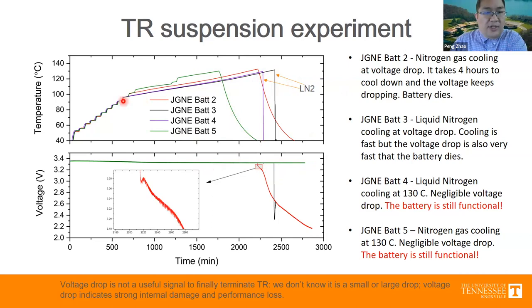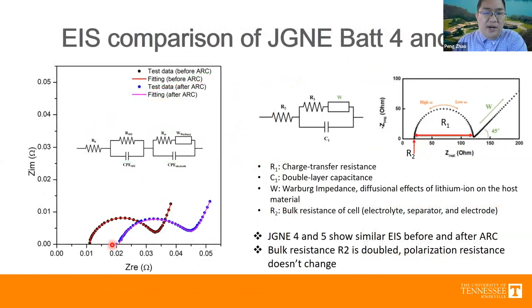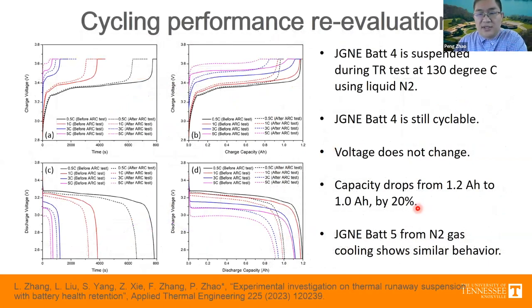For all these cells, the thermal runaway starts at about 100 degrees Celsius. At 130 degrees Celsius, there has already been some heat release from exothermic reactions. But eventually, as you can see, if we select the correct critical temperature, we are able to save the functionality of cells 4 and 5. We also compare the performance of cells 4 and 5 before and after being saved from the thermal runaway test. What we found is internal resistance doubles, its capacity drops by 20%. Its voltage stays the same, and they both are still functional. Okay.